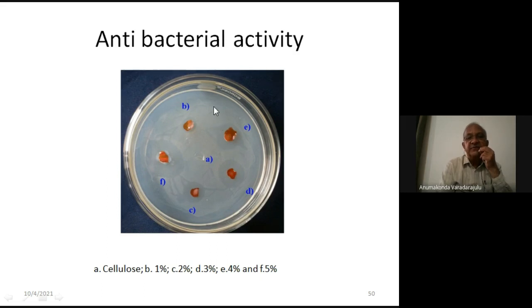For the antibacterial test, what we do is, first we take a gel and incubate it with bacteria, whatever bacteria we select. That gives a cloudy film. And if we introduce our film and place it here, this is our film with cellulose and curcumin, the colored film, and if you see it carefully, around this a clear zone is formed. Clear zones indicate the killing of bacteria. Once the bacteria is killed here, the translucence is lost and transparency is observed. This indicates that up to this portion, the bacteria is killed. The diameter is known as the antibacterial zone diameter.